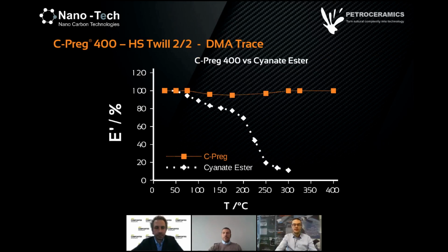And also some further DMA testing was performed to see what happens at different temperatures to the elastic modulus, which is here reported on a relative scale. In the case of C-Preg 400, you can see the huge stability even at high temperatures, such as 400 Celsius degrees, whereas in the case of a commonly utilized system, cyanate ester-based prepreg, you can see that we have degradation of the matrix at temperatures lower than 250 Celsius degrees, and these affect the Young modulus at the 3-point bending test, even at low temperature, as I said.